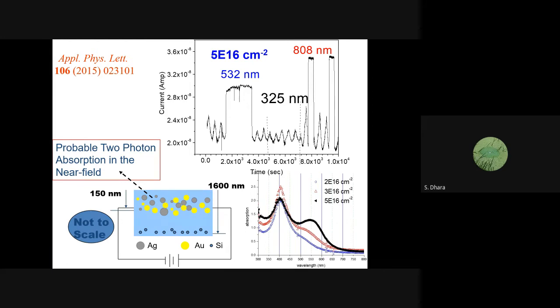In fact, beautiful examples are there, not from my group, but from some other group. The beauty is that thermal treatment would have spread the distribution of the nanoparticles throughout, because thermal diffusion would have taken place, but with the ion beam the localized diffusion coefficient is very low. The heating is extremely localized and very quick, a few microseconds or nanoseconds of interaction. So the gold nanoparticles will be in one particular layer, and if you connect to that layer, you can easily find both sides.